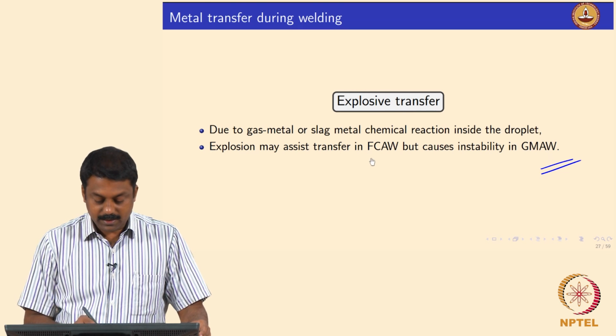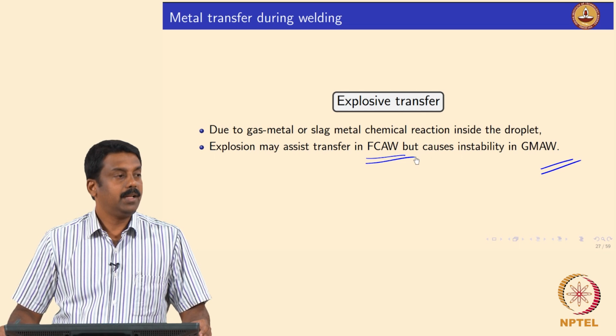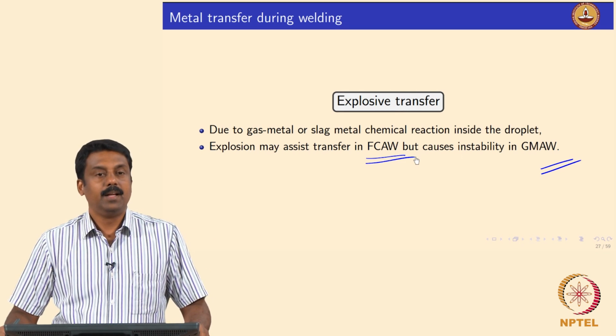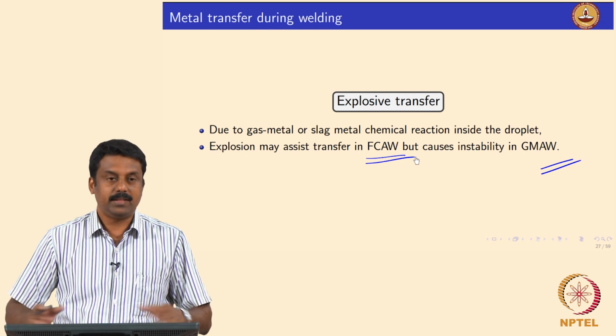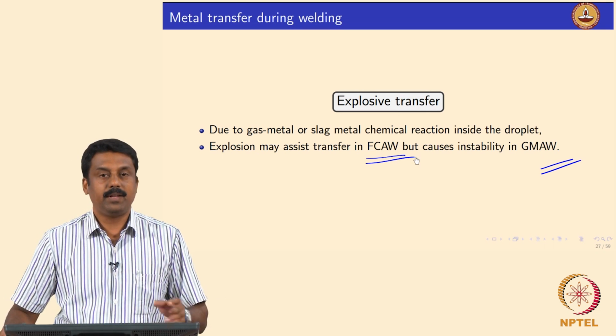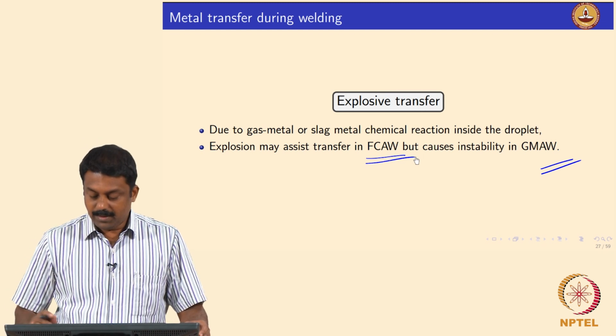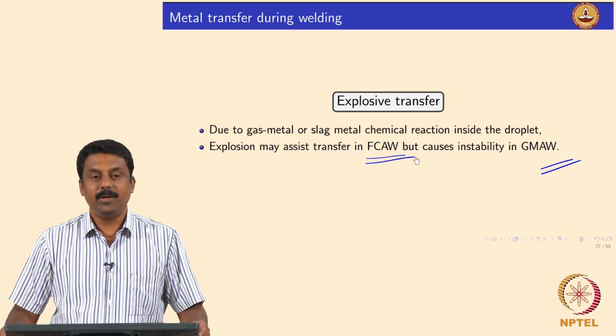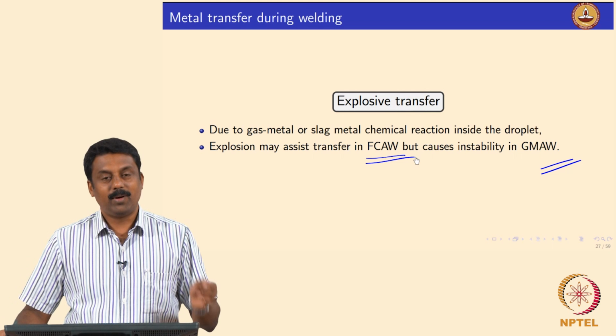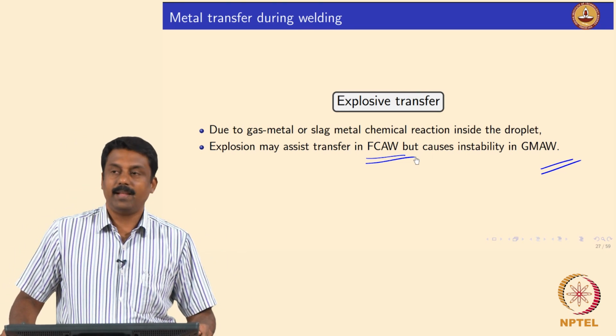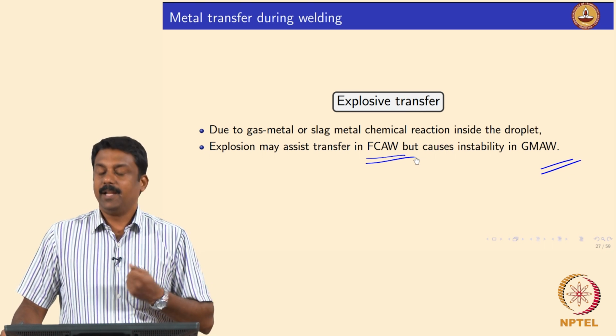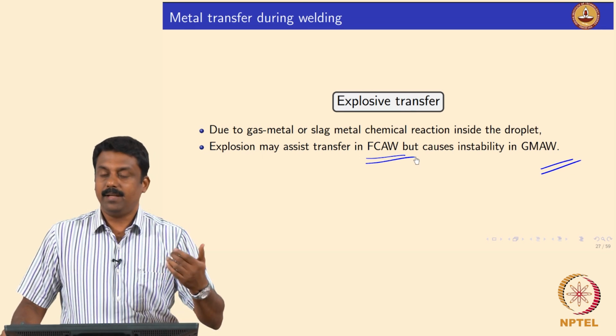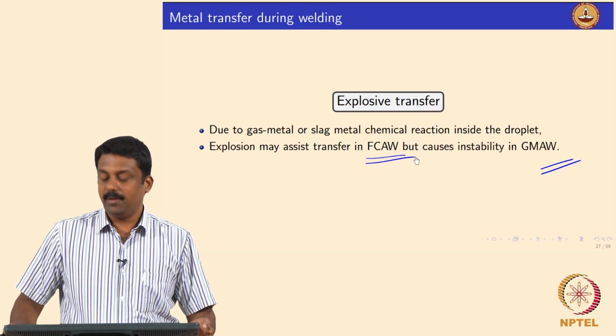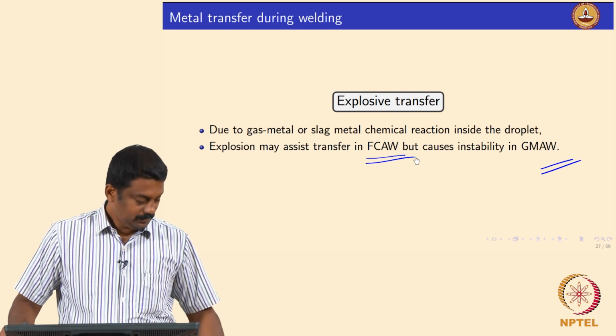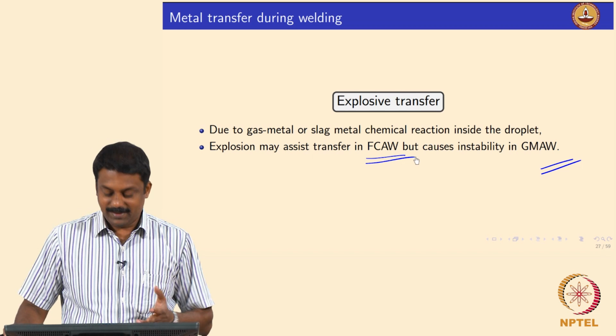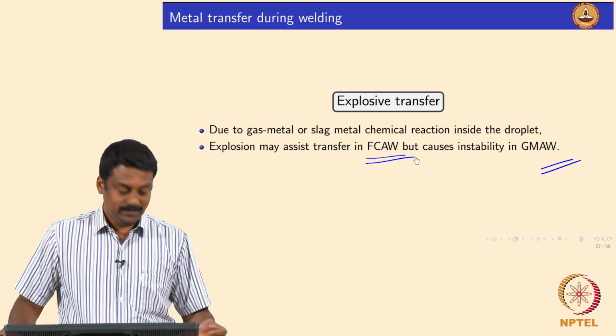In most cases it is used for spraying or coating, if you want to deposit FCAW wire onto the substrate, because you do not care about where exactly the droplet is going. So, you can do an explosive transfer by using high current and increase the productivity, but in GMAW it causes instability, because when you are welding you do not expect a droplet to explode and go everywhere. You want the droplet to go to the weld pool, the cavity. If you are using FCAW or any other electrode to deposit a layer, a coating, then we can use the explosive transfer. Okay, it's clear. Unfortunately, I don't have any video for this, because we never managed to get that. We need a very high current for explosive transfer. Good.